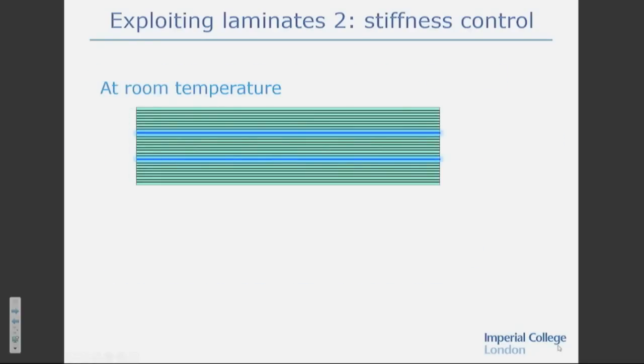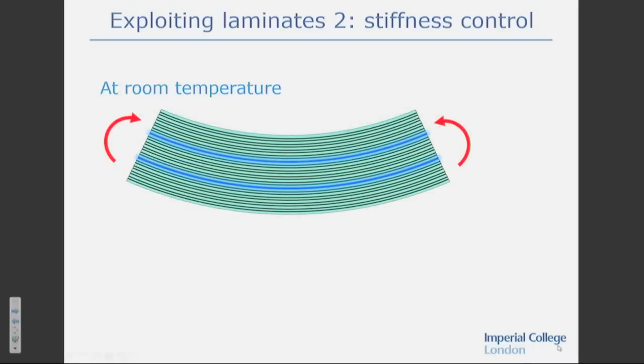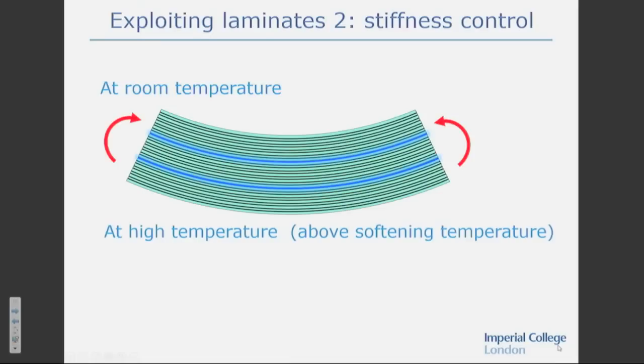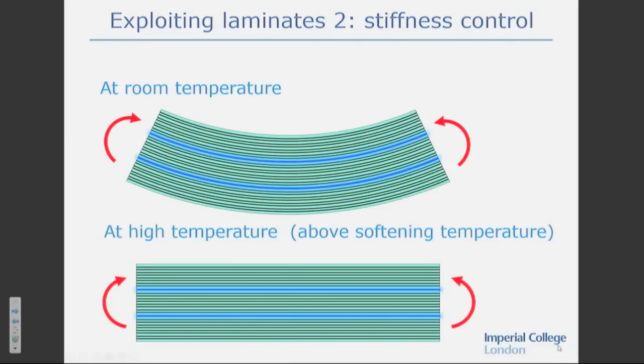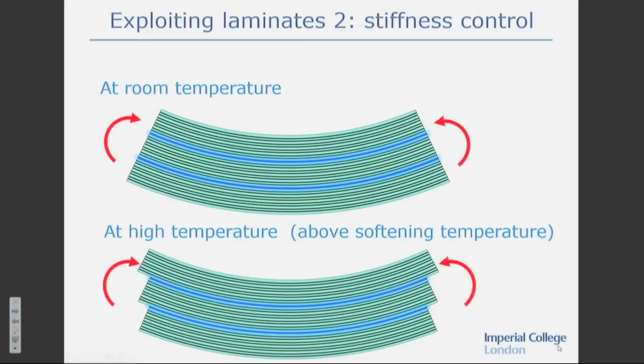So imagine we've got this laminate at room temperature and we apply a moment to it. Well, we saw before that at room temperature there's no sliding at the ends and it should have its full stiffness. But if we repeat this at a temperature above the softening temperature of the thermoplastic, then we'll get sliding like this, and we know that tells us the material is going to have low stiffness.